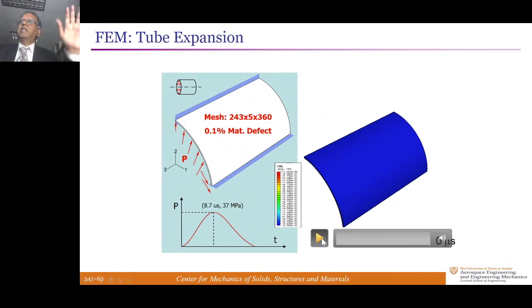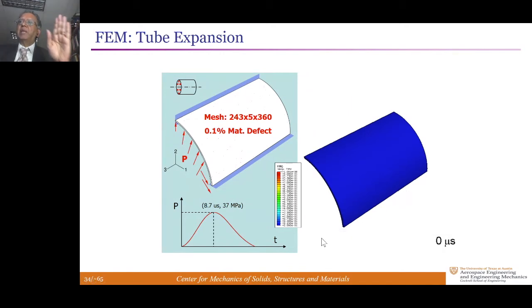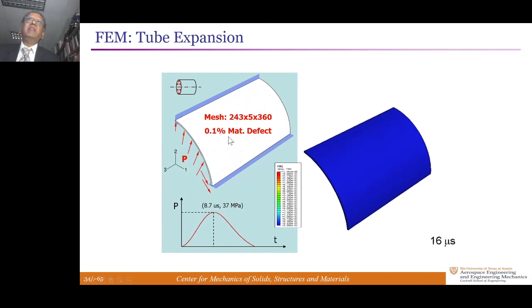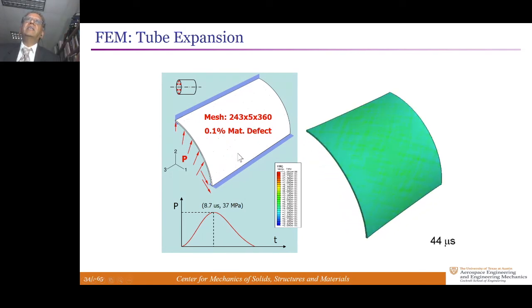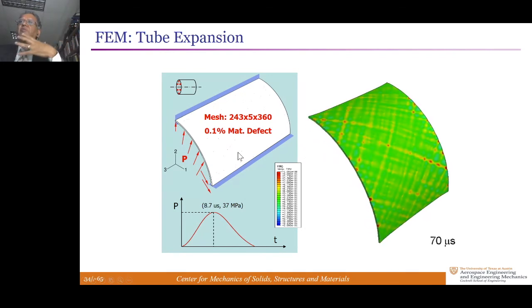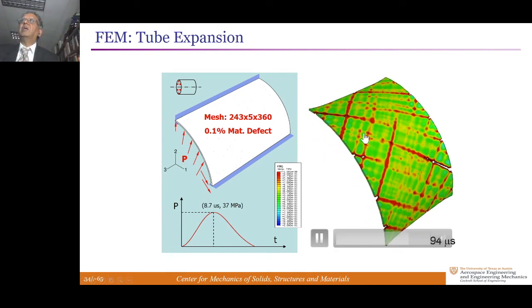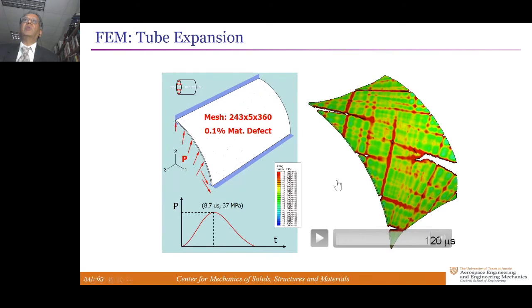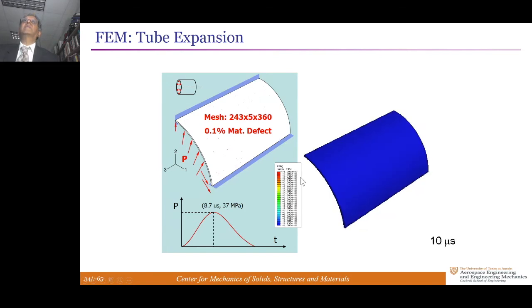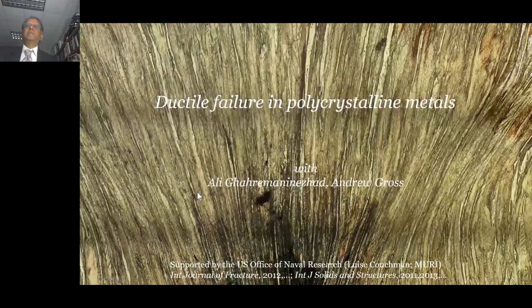One simulation, a very simple elastoplastic model, strain rate independent, but with a number of defects thrown in to create nucleation sites for these diffuse necks that are formed everywhere, recreates patterns that are very similar to what are observed here. There's not a quantitative match yet because we don't have a very good stress-strain curve to go to strain levels that are seen in these objects, but that's a story for a different time. All right, that's the first story of dynamic strain localization.